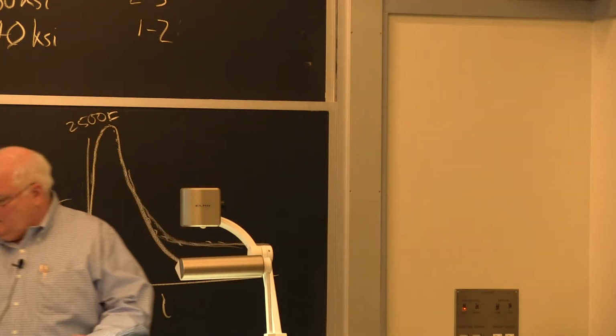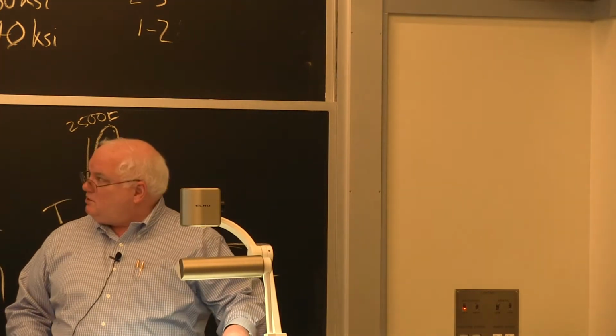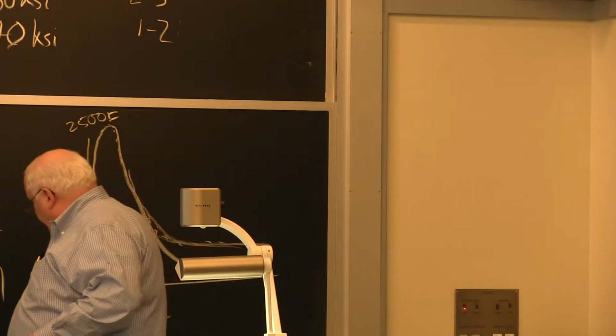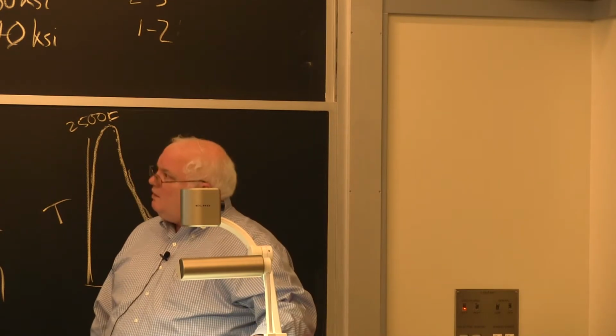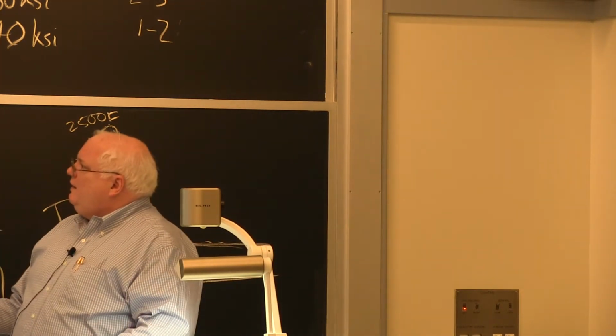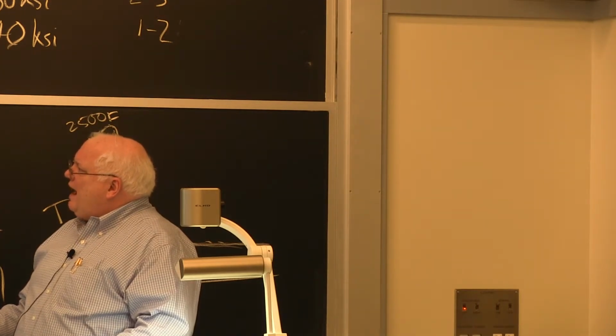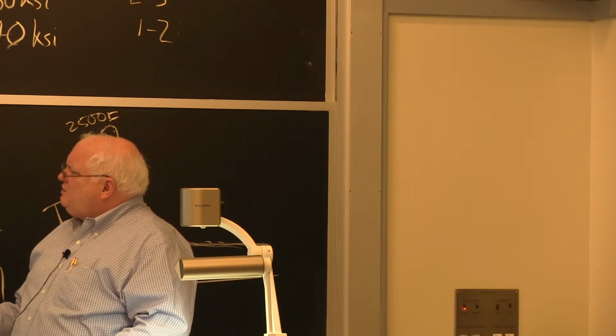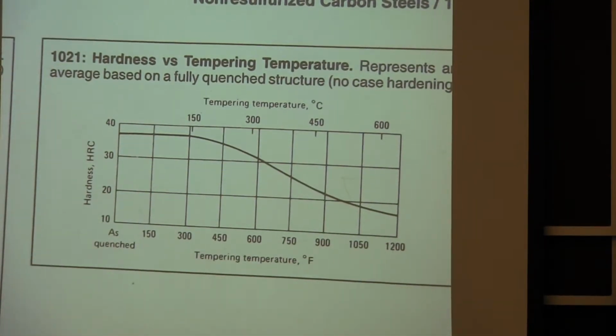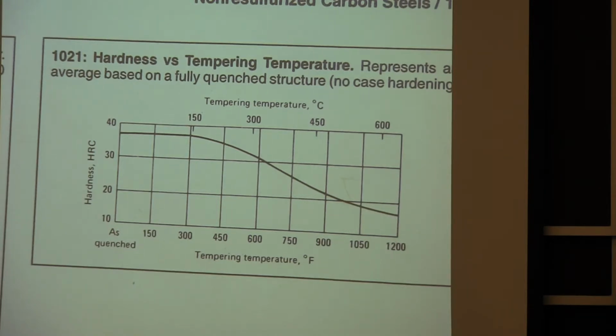And by tempering the steel, it turns out steels will lose their hardness. If you form martensite in the welding process, and you then hold it at temperature for an hour or whatever, once you get to 300 degrees centigrade, or 600 Fahrenheit, you start to see a drop off in hardness. And so if this is 300 Celsius, you actually will have enough time, this is probably log time as I've drawn this, you'll have enough time in here above what you would have if you were just letting it cool down and being quenched to room temperature by the steel.